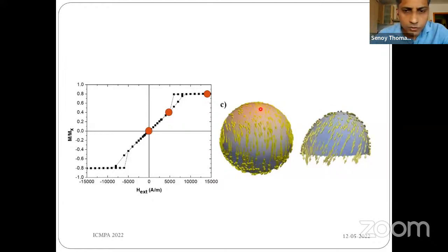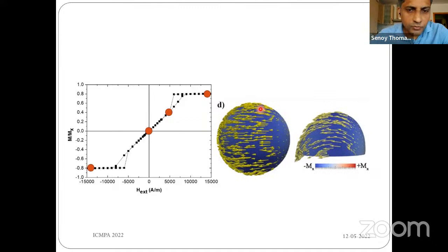And now if you increase the field in the opposite direction, a reverse onion state is obtained. So it means that in the asymmetric system, the shape anisotropy associated with the asymmetry is really influencing the magnetization reversal process.